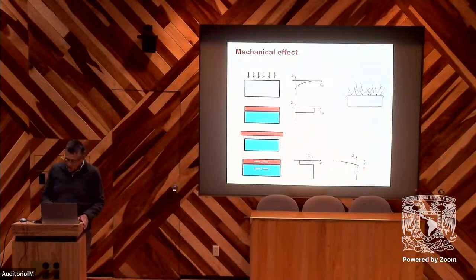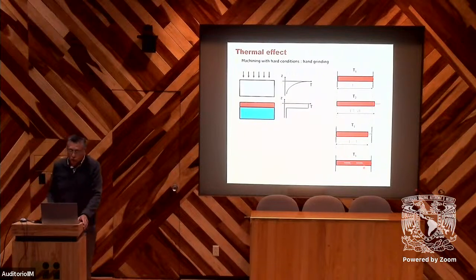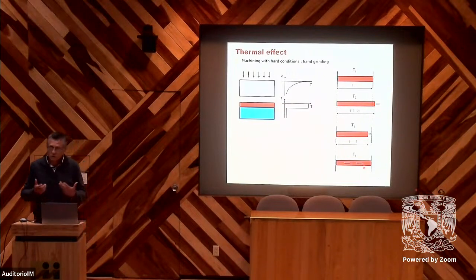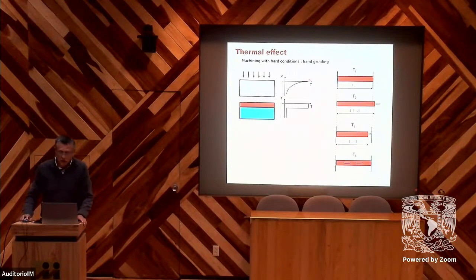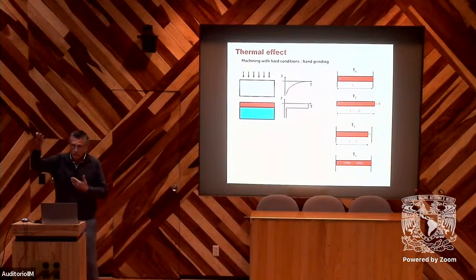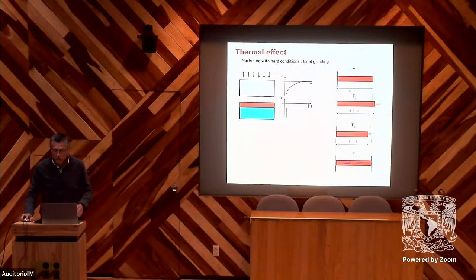Now, if we consider the thermal effect, for example, during welding or grinding with hard conditions, the thermal effect will be preponderant, and we will get a gradient of temperature. In the same way, consider that we have only two parts, the surface layer and the bulk of the material. So we have the heating of the near surface. If we start with initial temperature T1, with the initial length, and increase the temperature, we will have an expansion, but this expansion will be prevented by the bulk of the material. So that means we induce compression. And if this compression exceeds the yield stress, we will have a reduction of the initial length, L1 becomes less than L0.